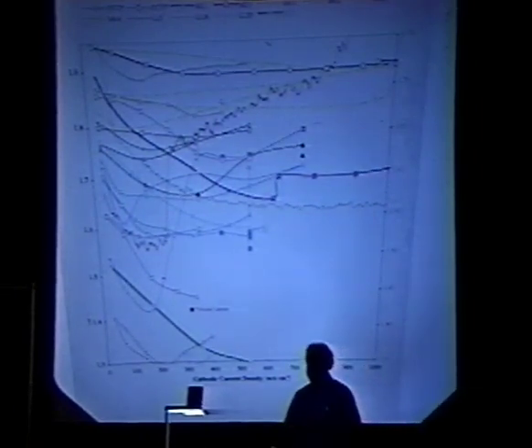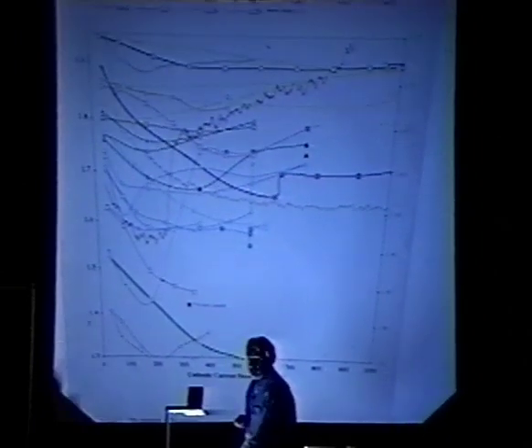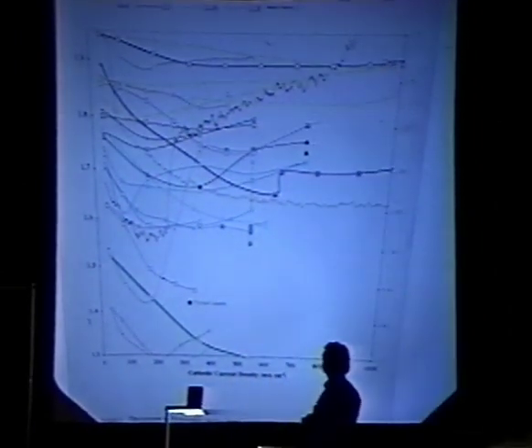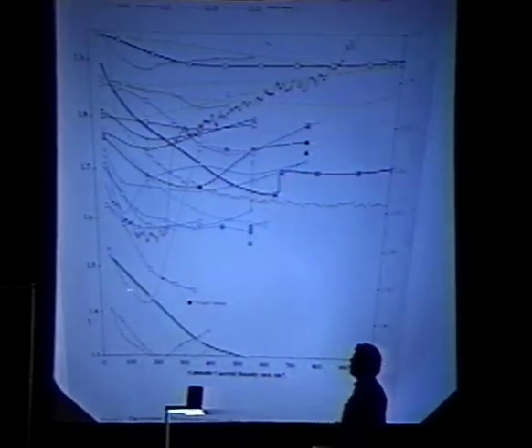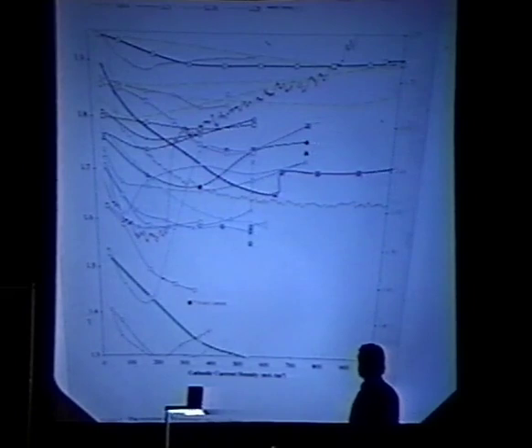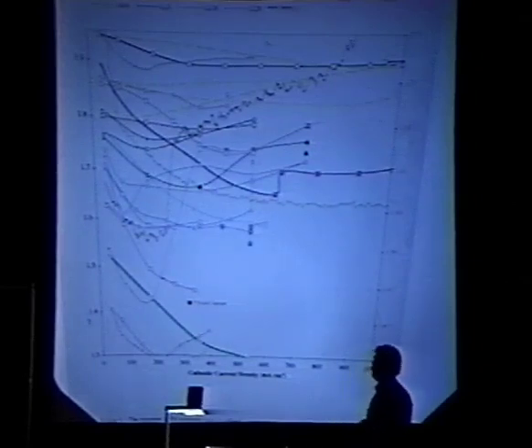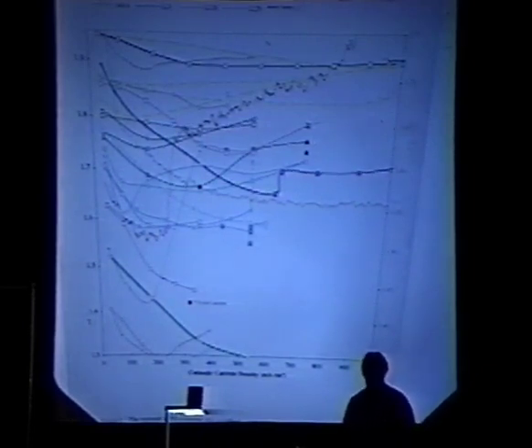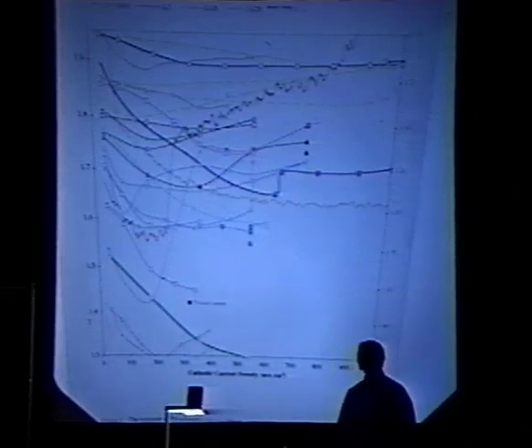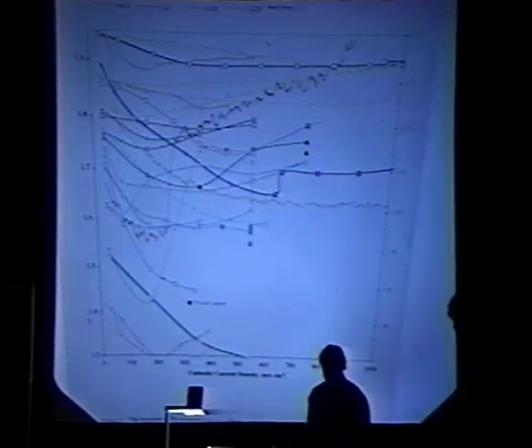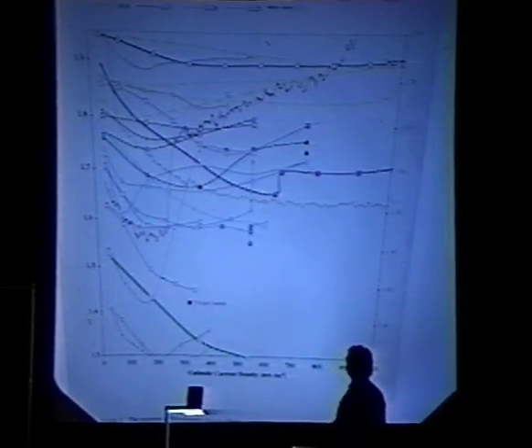We've done the same experiment 26 times. We've obtained these 26 wonderful results, all of them different. If you notice, they all start at a current density of 33 milliamps per square centimeter, increasing current density in this direction. What we're trying to do is drive the resistance down while we drive the current up. As you can see, in general, we do it, but the trajectories chosen by the cathodes in all of these experiments are remarkably disparate. In fact, depressingly disparate.